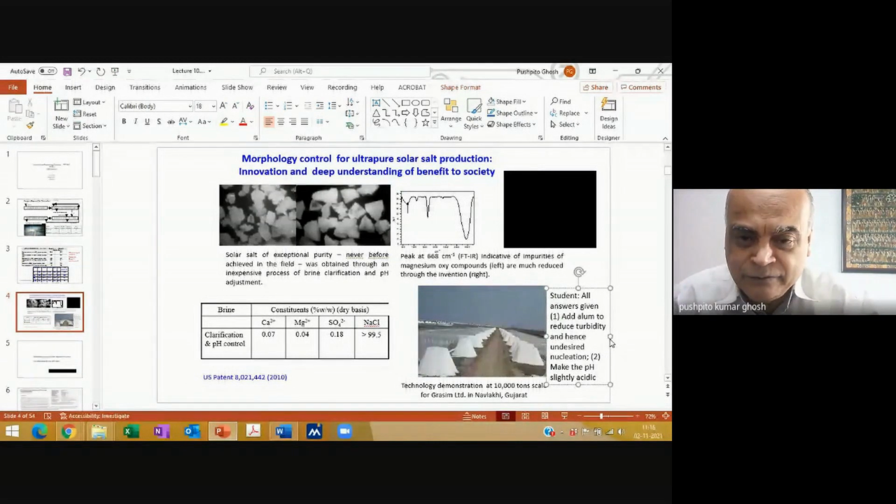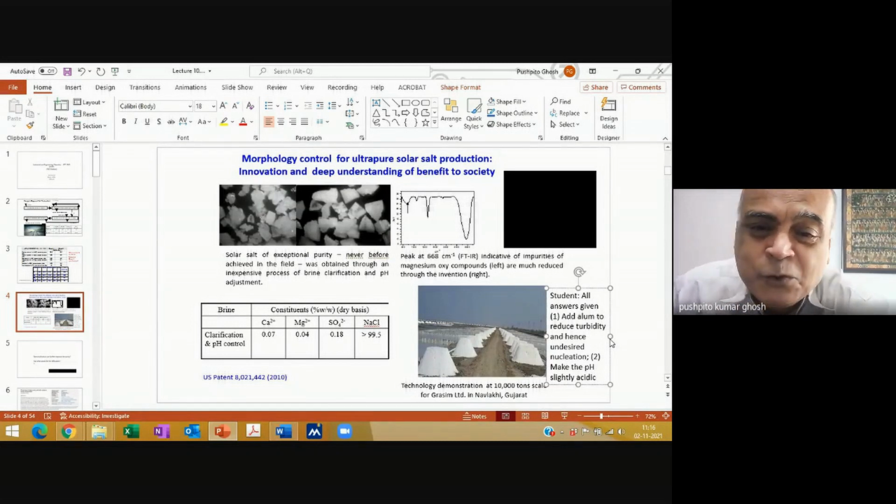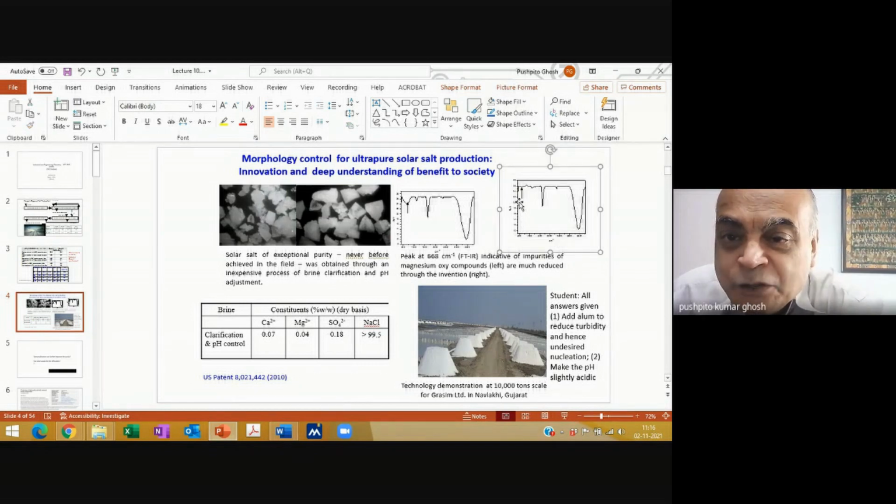That's it. There are 2 US patents granted for this. The 2 things that you mentioned, and you can see by reducing the pH to something like maybe a pH of around 5.5 to 6, you can actually almost make it disappear.